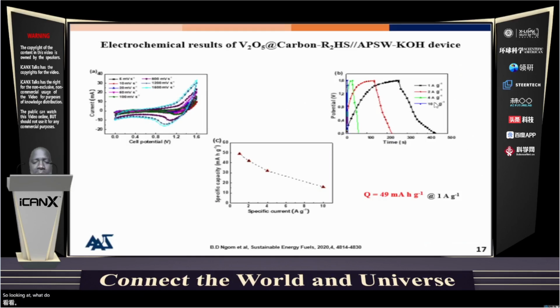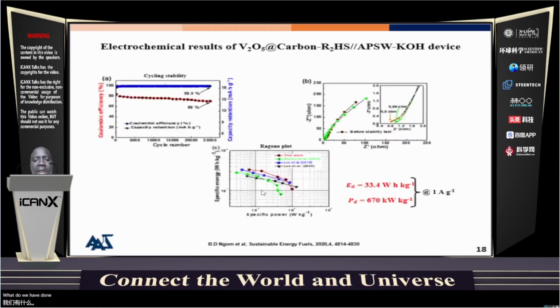Looking at the specific capacity, we could see that we are having 49 milliampere-hour per gram, which is the best result that we got from the hibiscus sabdariffa. And what we have done is that we have constructed a device using this V2O5 carbon, the dark red one, which we found to be the best one, as a positive electrode, and activated carbon from peanut shell as a negative electrode in 6 molar KOH to fabricate the device. Looking at the Coulombic efficiency of the device, we have 98.5, something like that, and 86 percent capacity retention, which is showing the best stability that our device is having.